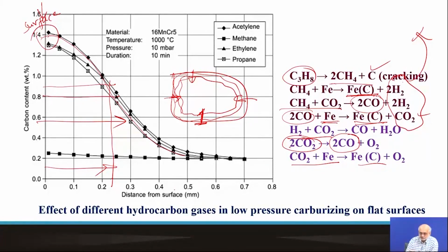So this is typically for low alloy steel. Here the temperature is slightly higher. We are talking about maintaining a certain pressure, but the time required is very small compared to 10 hours, 20 hours of pack carburizing, maybe a few hours, or at least close to an hour or two for liquid carburizing. And here in gas carburizing, it's much smaller. And we can have one of these charges, and what we see is in the case of acetylene, which decomposes faster and is a lower hydrocarbon, the carbon enrichment at the same depth is always higher. So methane, if we use only methane, then that's a very stable hydrocarbon. It doesn't dissociate, so it doesn't make any difference at all. So one has to use essentially these unsaturated hydrocarbons, which will be able to release carbon during the dissociation process, and that carbon can get adsorbed onto the surface.